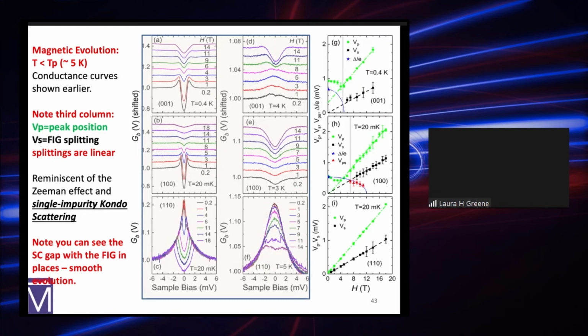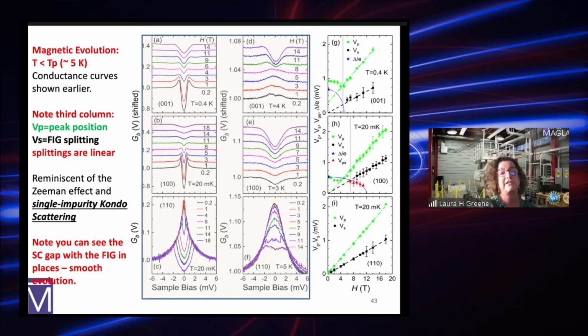That is a great question, and I wish we could do that. One of the advantages of planar tunneling is that the junctions are robust. We can look at them in different fields. It's easy to go up to 18 Tesla. Not easy, but it takes a lot of work on the junctions, but it's possible to stick it in different fields, look at it in different orientations, change the orientation of the field, and do junctions at different faces up to 18 Tesla that we've done. We're trying to go to 45 Tesla, but we haven't run the hybrid in a while. We're just starting to run it again.